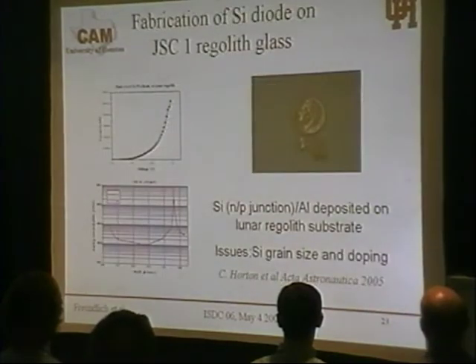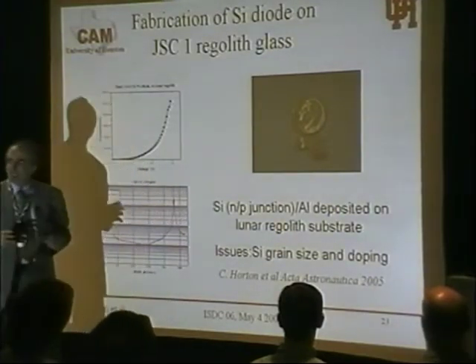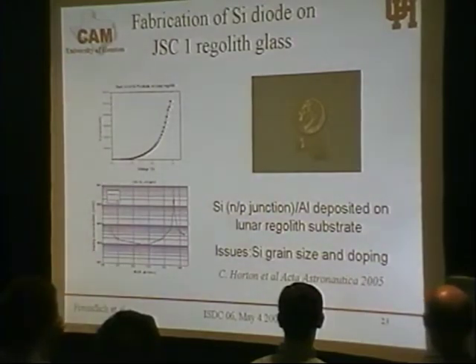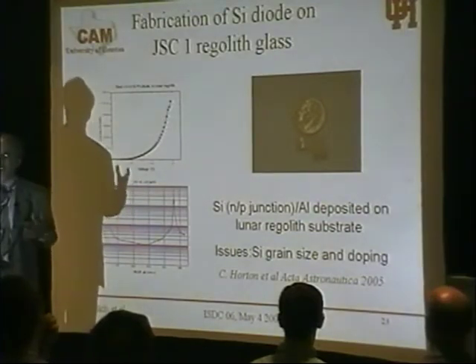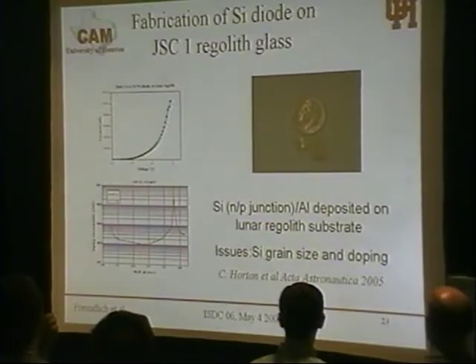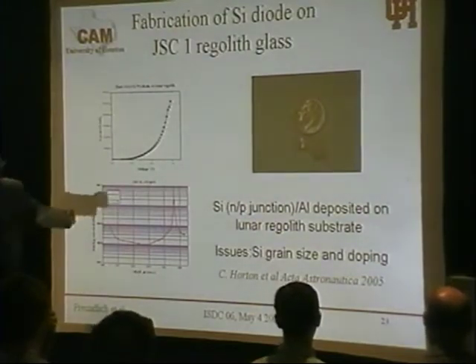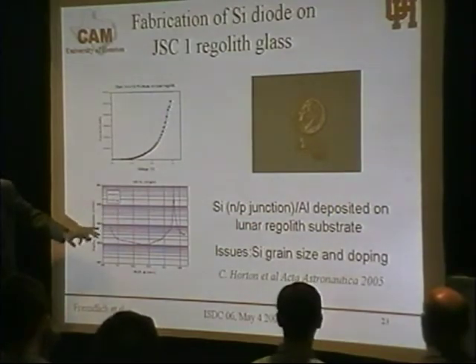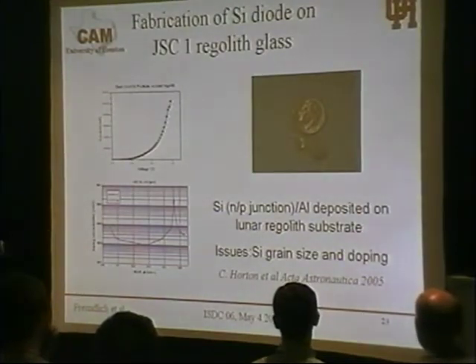We also just started making silicon diodes. For these, we have two issues, and I will get back to that. One is the grain size, because if the grain size is very small, you may get something close to amorphous, and amorphous silicon is not going to give you any light response unless you hydrogenate it. Hydrogenation is not something readily available on demand. It's possible there will be lots of water on the South Pole and that will solve the problem, but right now we're assuming it's not there. The second issue was doping, but we have pretty much solved that one. We are right now at a doping level of about 10 parts per million; here it was probably about 100 parts per million. Next.